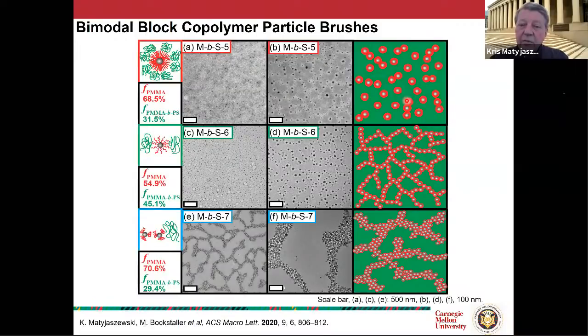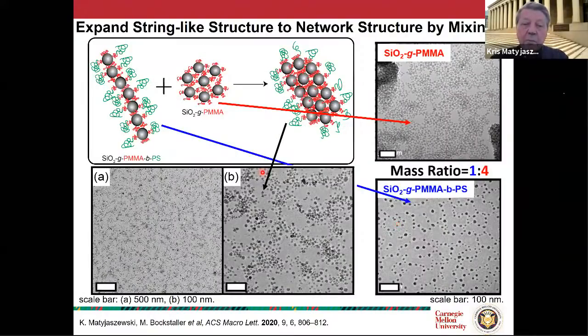So this gives you a very intriguing system. This is a possibility of having this type of strings or train, if you wish. And depending now on graft density, if you have a very low one, in that case, you will have even some nanoparticles not grafted. They would be sticking inside these PS grafted systems. You can do the same by simply mixing these with the naked PMMA, and they would be loaded inside. In that case, these structures loaded with these structures will give you this type of cluster.